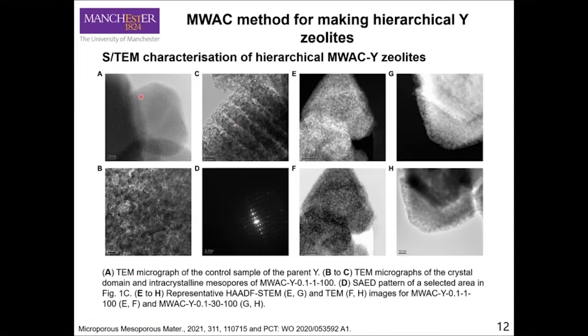As you can see over here, this one is the parent, the pristine zeolite Y, which is purely microporous, only with micropores. But after the treatment, you can see the combination of mesopores. The crystalline fringe can still be seen over here. Quite important, from this TEM image you can see the edges of the zeolite Y crystals have been etched out. And this is quite important. This provides a large entrance for bulky molecules to diffuse into the internal surface of the materials.